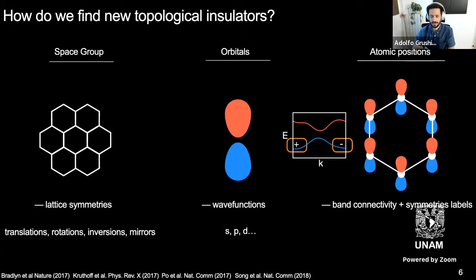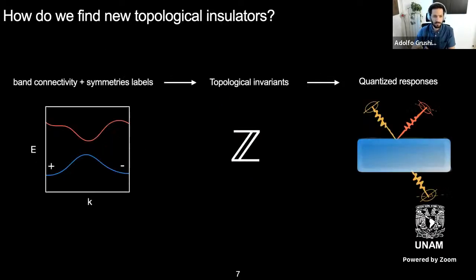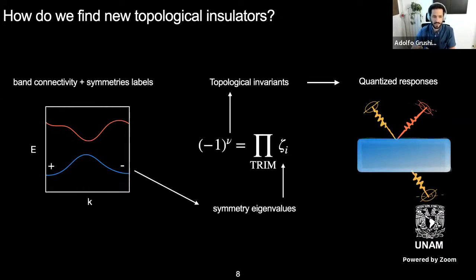And how do these enter the calculation of the topological invariant? Well, instead of having to know everything that happens with the wave function in all momenta, you can just take the specific points like 0 or pi, what we call high symmetry momenta, and multiply literally these eigenvalues of the symmetries. In this case, for example, inversion eigenvalues at the time reversal invariant momenta. It just means special momenta in the Brillouin zone that transform nicely with respect to the symmetries of the system. And you'll get, in the case of inversion, either a plus or a minus 1, and that's your topological invariant, essentially.